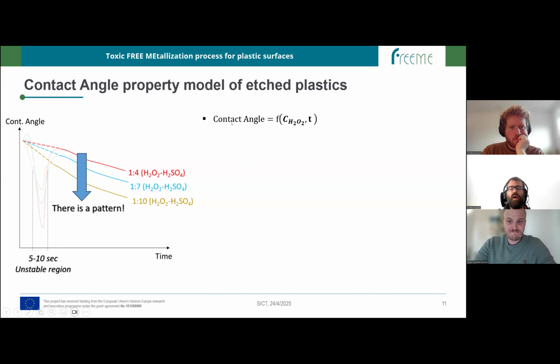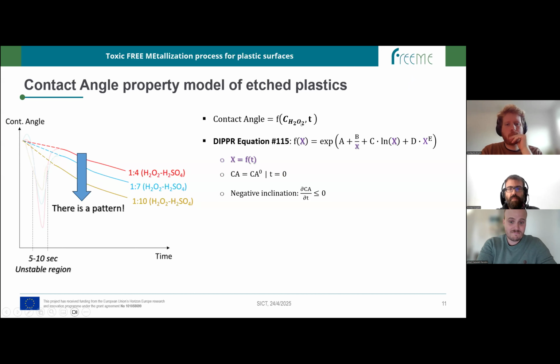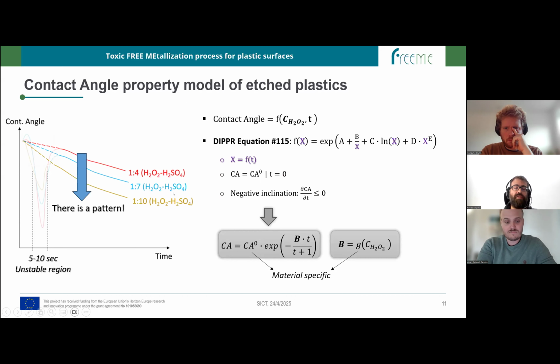So here we have an incentive to correlate contact angle with the Piranha concentration and the time. And by being inspired by a DIPPR Equation #115 model and by considering fundamental boundary conditions, like at time zero, you have the initial contact angle of the non-etched substrate, while at the same time contact angle is reducing versus time, we have developed a first model, where you can see the estimation of the contact angle, while different parts of the model, parameters, and also equations inside the model, are material specific. And here you can see also the effect of the time. And here you can see that we have another parameter in the model, which is also affected by the concentration of the hydrogen peroxide.